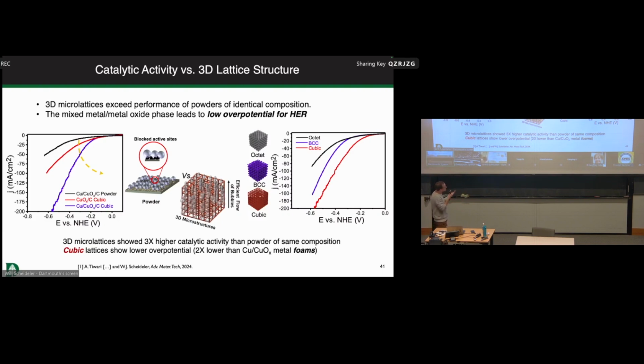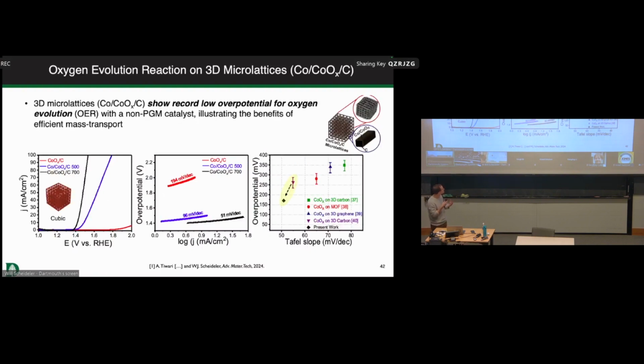And the interesting advantages, one, are that the three-dimensional structure has more accessible surface area. It doesn't get blocked by the bubbles. So it has higher activity than the same material in the form of a powder. The other thing is that the activity of the catalyst depends on the three-dimensional structure. I don't know if we expected to see this when we started out, but it was really an interesting result that showed that the way the bubble moves is really important. If the bubble gets stuck in lattices that have a more complex internal unit cell like the octet, then you essentially can't allow the electrolyte to access the rest of the material and complete the reaction.